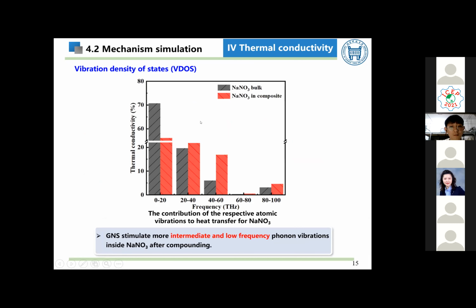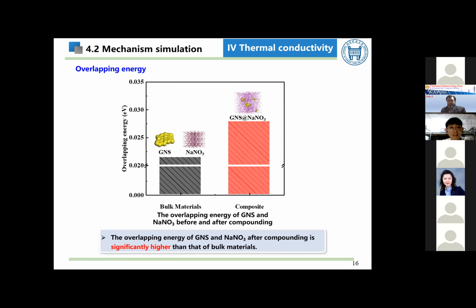The contribution of phonon vibration in different frequency to the thermal conductivity was calculated. It can be seen that the contribution of low and intermediate frequency phonon vibration increases after compounding. This indicates that GNS stimulates more intermediate and low frequency phonon vibrations inside sodium nitrate, which accounts for the increased thermal conductivity too. Besides, we quantitatively calculate the overlapping phonon energy of GNS and sodium nitrate before and after compounding.